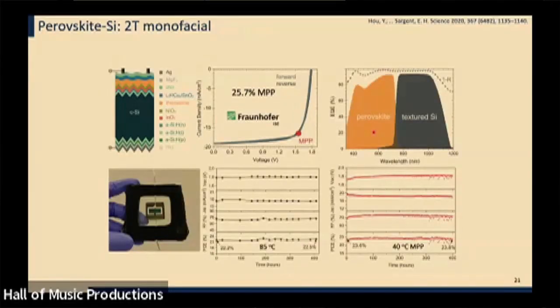So that was the first optimization, was to find a suitable pyramid size. And then the next step was to build an integrated device with this technology that evenly apportioned the photon current between the silicon, which is what I show on the top right here in the blue, and the perovskites, and it needed to current match. Because these were being connected together in series, we had to equalize their currents and optimize the choice of band gap in the perovskite layer. And as a result of that, we're able to advance the efficiency of these solar cells by combining the two active layers together. And as you can see here, also achieve an improvement in the sustained performance, so the continuous, reliable operating performance of the devices.